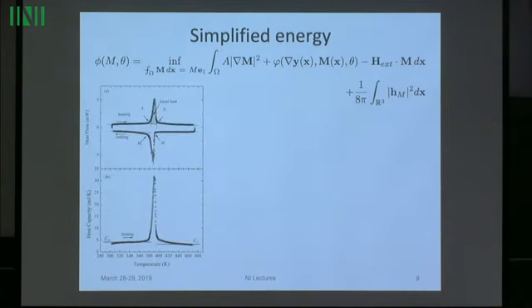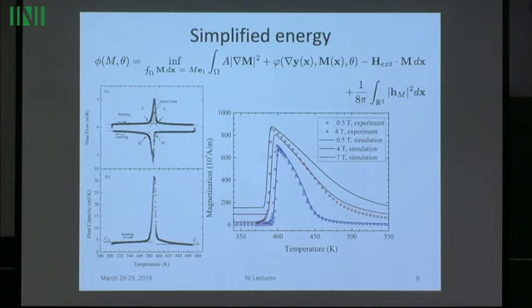For example, the derivative of phi with respect to temperature, taken on each side of the transformation, the difference is the entropy. And the change in entropy in a phase transformation can be related directly to the latent heat, so the area under this peak. So somehow directly from experiment, without exactly evaluating this constrained infimum, we can get information about the derivative of phi with respect to theta. And one expects a double well energy for this phi, and many things about that we can evaluate directly from experiment using calorimetry.